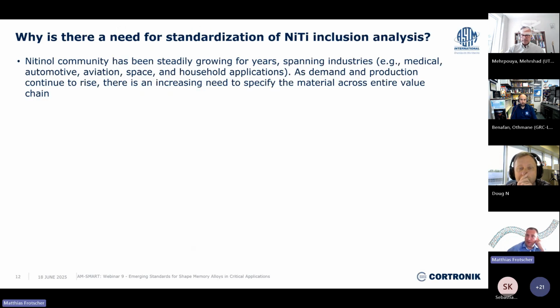Typically, a material specification should not describe test methods. It should reference a recommended test method, though. On the other hand, a test method should not include acceptance criteria for materials. These are two distinct types of standards that are not to be mixed up. Unfortunately, this has happened in the past when those standards were initially developed.